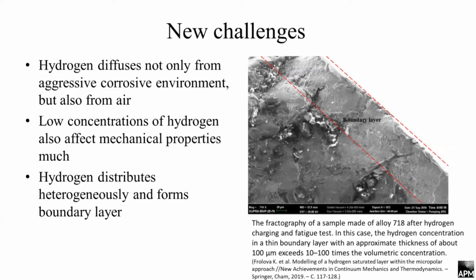What is new, and why am I interested in this? Recent experiments show that hydrogen diffuses not only from an aggressive corrosive environment, but also from the air. Metal can catch hydrogen from the water vapor in the air. So basically, hydrogen embrittlement happens not only in corrosive environments. The second experimental fact is that low concentrations of hydrogen also affect mechanical properties, and they do it a lot. So a lot of models which propose that hydrogen affects those metals only at high concentrations actually don't work.